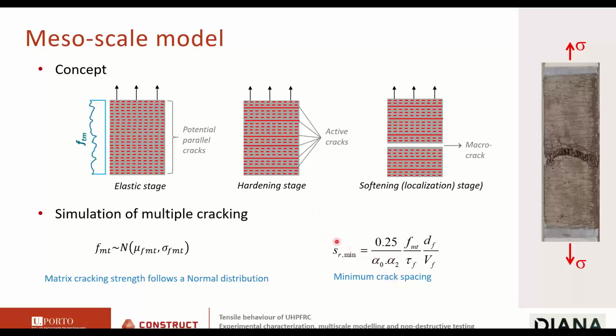So how do we use this? For instance, if this crack has opened, and the neighboring cracks are at a distance from this one smaller than the minimum crack spacing, we don't allow these cracks to open, and only the cracks that are spaced more than this value can be activated.